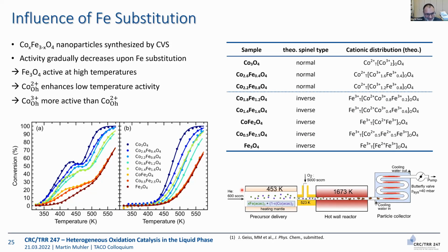These are not yet published results, and a different way to get spinel nanoparticles by chemical vapor synthesis. That means the whole catalyst synthesis is performed in the gas phase at high temperatures. That means we get nanoparticles, but they don't agglomerate because everything is highly diluted in the gas phase. And these nanoparticles have then a very high structural quality. And this is now what you get just by inorganic solid state chemistry, site occupancies, when you go from the cobalt oxide to the iron oxide.